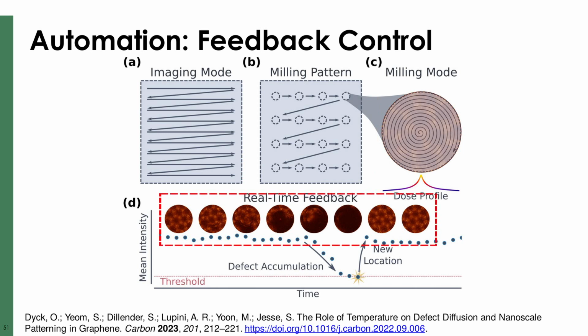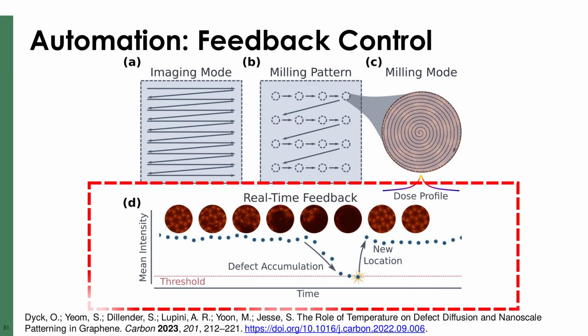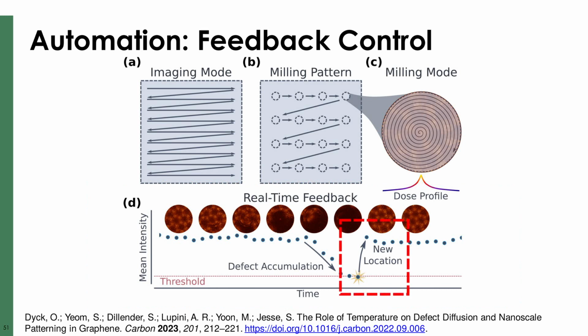This allows us to create a small image of the sample that can be updated with each pass of the spiral. The majority of the dose is concentrated at the center of the spiral where we want to create a hole, but the extended tails of the dose profile allow us to obtain a larger image of the local structure. We then use the average intensity of the spiral image as a feedback control and set a lower threshold that indicates when a successful hole has been milled. When this threshold is hit, the computer automatically advances to the next position, and in this way we can pattern holes in graphene in a fully automated fashion and start to get some statistics on how this process proceeds.